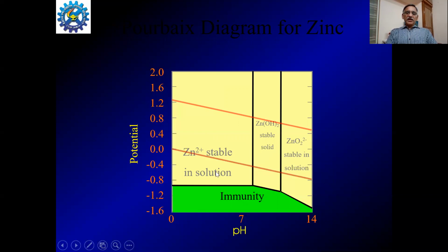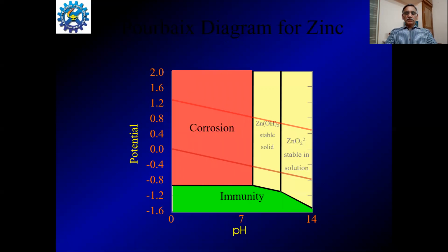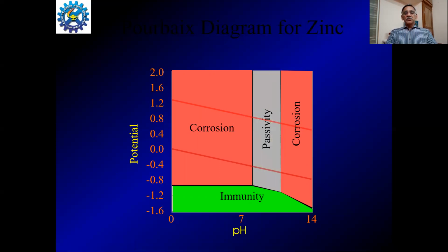The area where zinc is available in ionic form, here and here, is called the corrosion domain. Because of corrosion, in these big areas of huge potential range and pHs, we have zinc existing in the form of ions, and hence they are called the corrosion domain or corrosion region. A small narrow region where zinc hydroxide in solid form is stable is called passive. Here there will be an initial corrosion so that the zinc metal gets transformed to zinc hydroxide, but it will cover the zinc surface and form a film over the surface, and hence the metal will become passive.